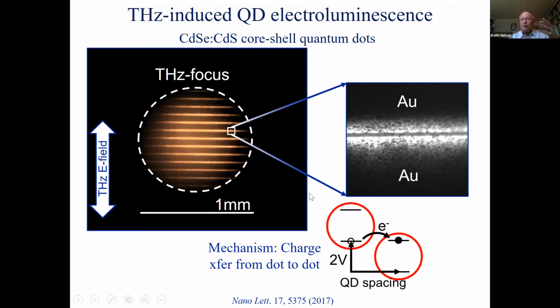What it's doing is charge transfer. It's strong enough to yank electrons off of one dot and drive them onto the next one. Then the field is gone and the electrons jump back and there's radiative recombination and light gets emitted. So this is a really unusual kind of electroluminescence to produce this signal that you're seeing. And the really important message is that terahertz fields are strong enough to do charge transfer, and charge transfer, electron transfer, is crucially important for lots and lots of chemistry: ground state chemistry, photochemistry, photocatalysis, and so forth. Terahertz pulses can be used to induce that, to make that happen in unique ways.